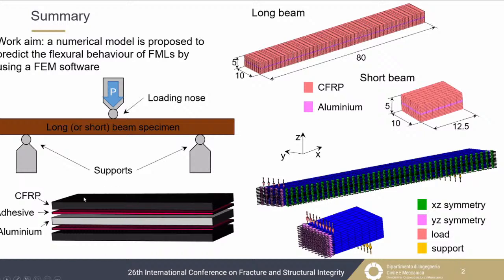The material is in this image. We simulated the material composed of a central metal sheet made of aluminum and two external CFRP layers that were connected to the aluminum using an adhesive, a structural adhesive.